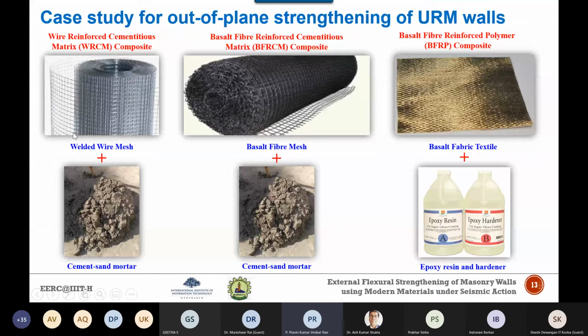Now, if you see, this wire mesh and fiber mesh have been used in conjunction with the inorganic matrix. Inorganic matrix means it may be a cement sand mortar, a lime mortar, or any cementitious matrix. Whereas in case of the textile, we have used a material called basalt, and in order to join this material to the masonry wall, we are using a binding agent called organic matrix, which comes under the category of epoxy resins, and especially epoxy hardeners have been used.